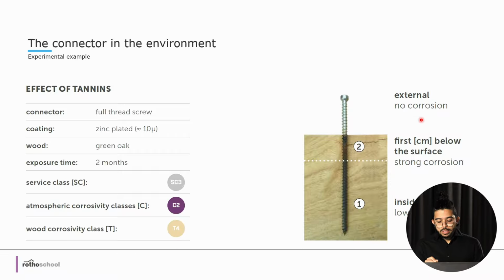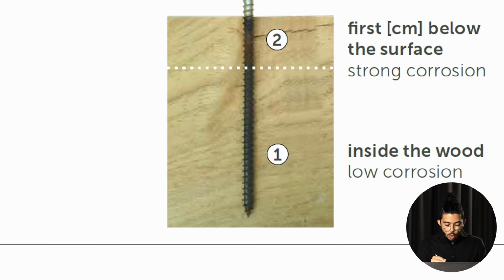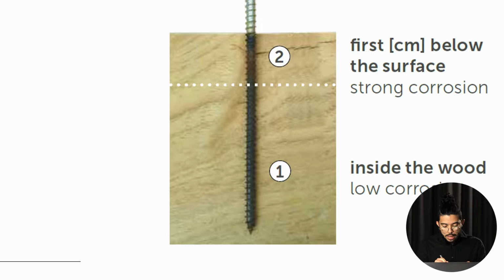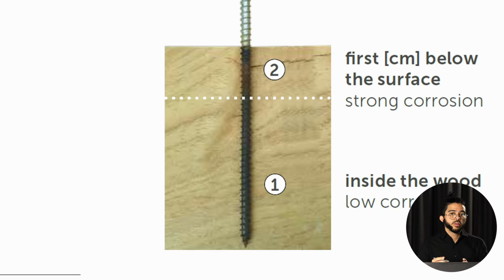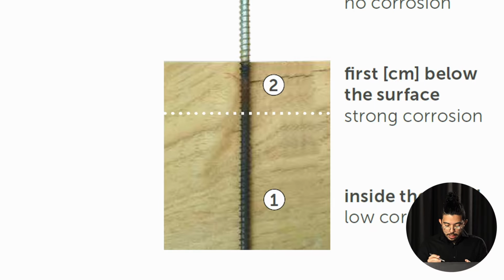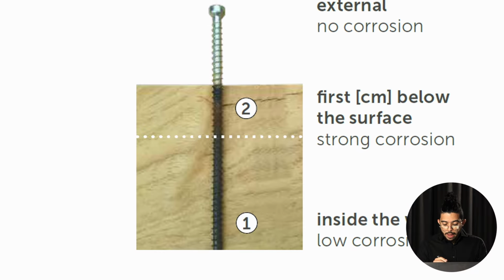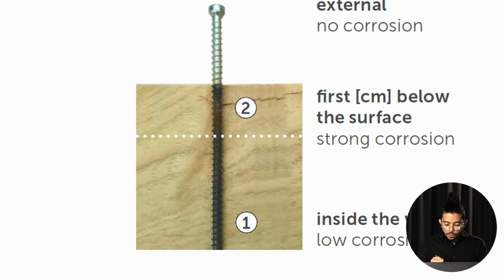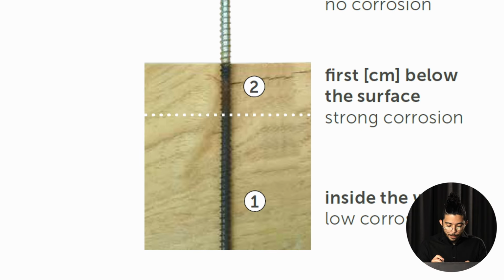In the exterior, you will see no corrosion because it was a C2 atmospheric corrosion class, so in that period of time no corrosion happened. Inside of the wood, you will see a black coating, but you won't see rust, neither red rust nor white rust. You will see a black surface, and so you would deduce it is low corrosion. But in the first centimeters below the surface, you will see the red rust. That is strong corrosion.